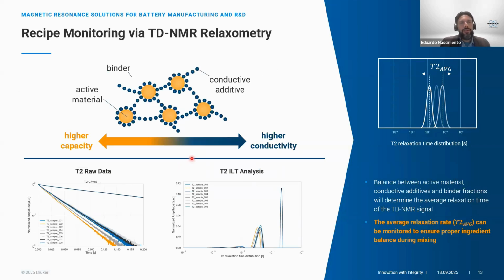So the second application that you have for TD-NMR in this area is recipe monitoring, as you said. And the principle here is that every time a component of your slurry changes, the relaxation rate will also change. So now we are not talking about how broad this peak is, but the position of this peak in this distribution graphic. And this can support you as well in the development of new recipes, and even, as I said, if you have in-process variation or problems with the origin of the raw materials that you are using.